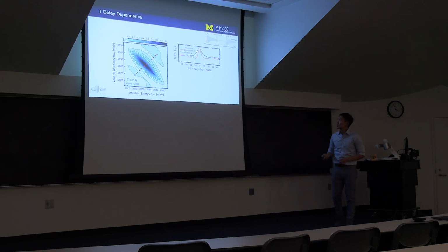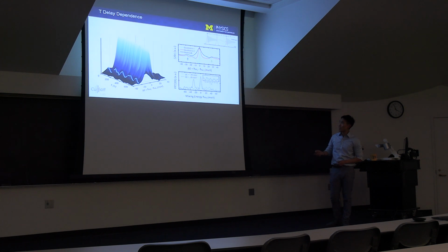So what we do is we take the one quantum vector as a function of capital T and Fourier transform the complex values of the sidebands. And what we find is that the Stokes sideband exhibits strong quantum oscillations at the LO phonon energy, which indicates coherences between the ladder states. And I want to mention that this one-sided spectrum, which consists of only a negative energy peak, is a strong indication of intraband coherences between vibrational states. So if the states were electronic in nature, you would see a positive energy sideband as well.